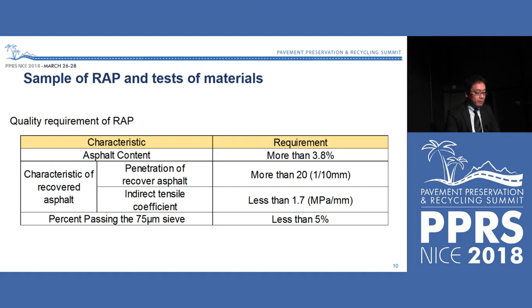Let me mention sampling of RAP and criteria of materials. The representative RAP and virgin aggregates are sampled from the storage pile. The extraction test and the recovery test of RAP, classified by predetermined particle size, are conducted. And the aggregate particle size and penetration or indirect tensile coefficients are then measured. To use RAP in recycled asphalt mixture, RAP needs to satisfy the criteria of this table.